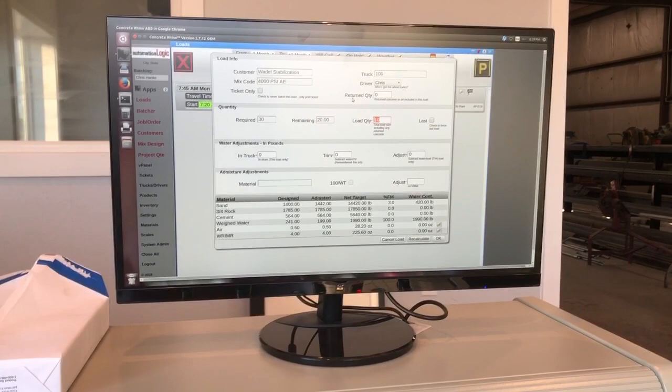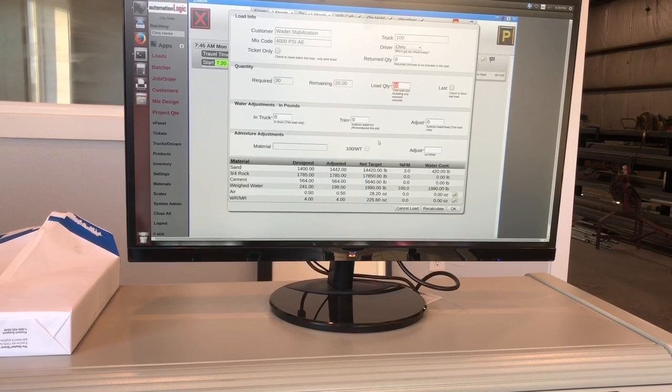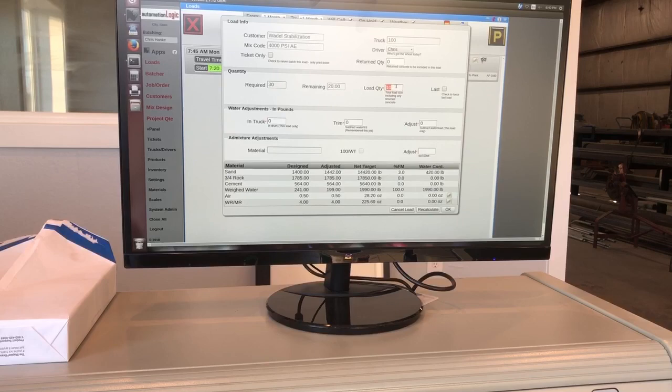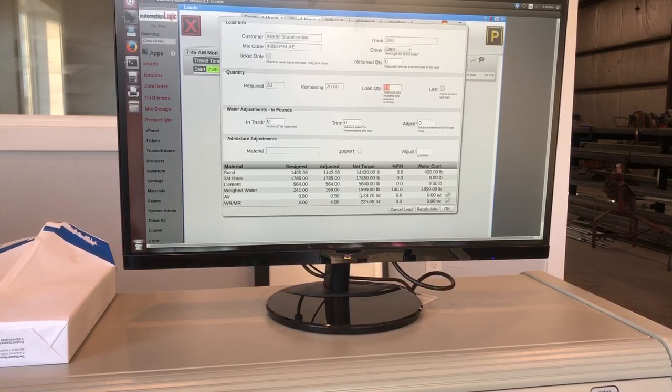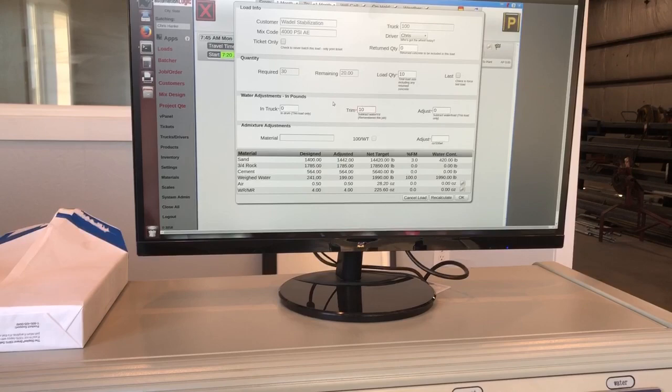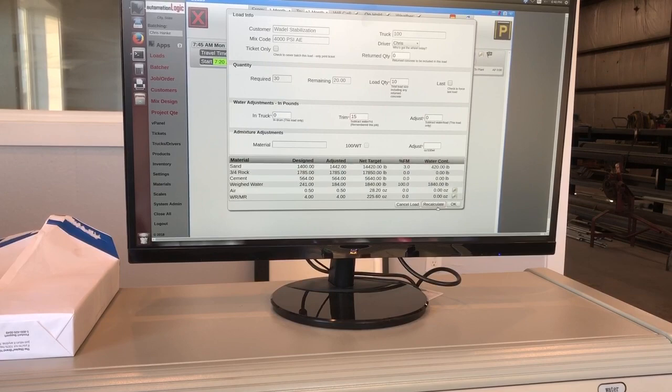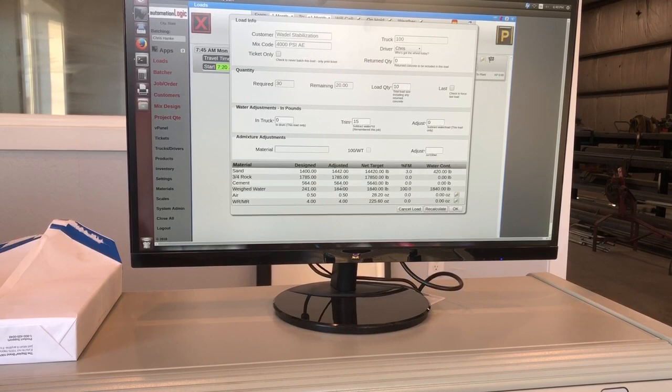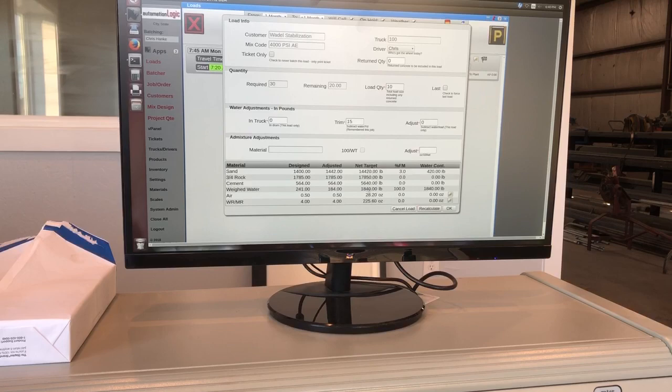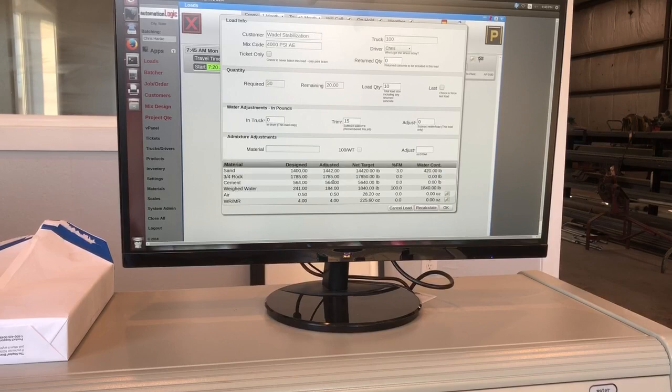When I want to load this, I'll just grab the truck out of the parking lot. Take it on top of the load. And this screen populates. You can adjust your water here or admixtures. 10 yard load. I could also adjust my load quantity in here. Let's just say that I'm happy with all of these numbers, especially the water. Like if it rained last night, let's just say it rained last night. I want to trim maybe 10 pounds, maybe 20 or 15 pounds at a yard. I'm going to recalculate. And that takes my weighed water down from 241 pounds to 184 pounds, a total of 1840 pounds. I'm happy with that. You can also just divide out how many pounds are in a gallon. When I convert to gallons, I click okay.